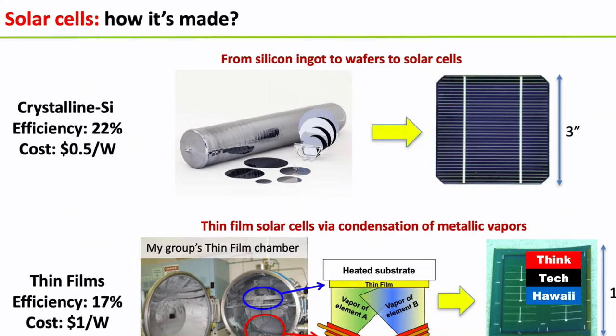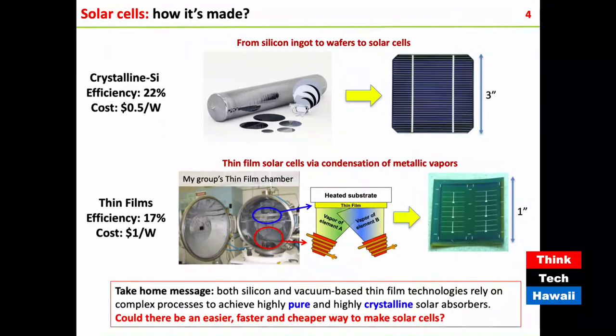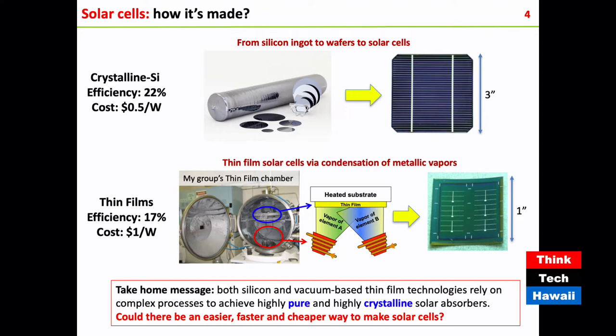So the standard crystalline silicon cells actually come from an ingot of silicon, which is like sand. So you start with sand, you melt the quartz or the sand, and there are some chemical reactions with, I believe, graphite to extract the oxygen from the silicon oxide, to end up with the pure silicon element. Right. And then on top of that molten pool of silicon, you put a very small seed of silicon in contact with the liquid. And as you pull the seed very slowly away from the liquid, what's stuck on the seed will crystallize. Right. And as you go, you're going to form that large ingot.